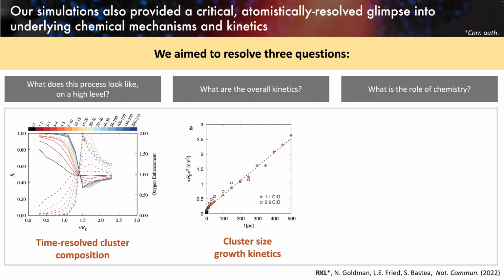We can also ask about kinetics on a larger scale. In this plot, we're looking at a cube of the average particle radius as a function of time. We see there's two regimes here that's kind of difficult to see, but we have an S-shaped regime and then a linear regime. This follows along with what we'd expect from classical nucleation kinetics, where this linear regime tells us we've hit an Ostwald ripening cluster growth mechanism.